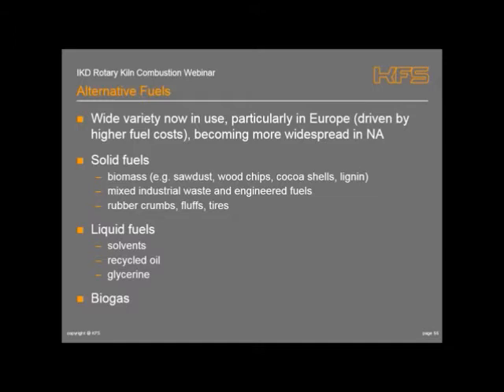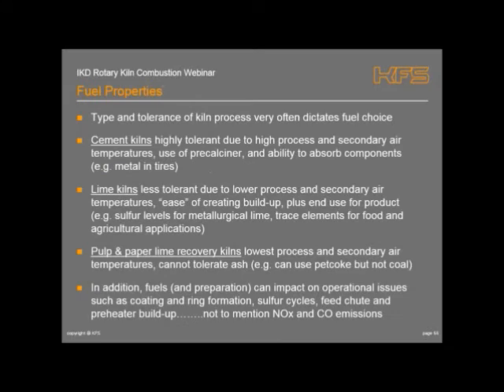The fuel properties are influenced by the tolerance of the kiln process they're going into. A cement kiln is very tolerant, it can take most things — even tires, where the metal in the tires is actually included as a bonus. It's a high temperature process, the secondary air temperatures are very high and it's able to absorb a lot of the materials into the product, which is good.